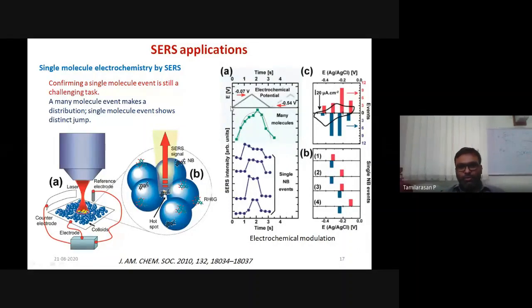It's just a cyclic voltammogram. When they scan it, they got a CV of something like this. Okay, this is for the bulk. For the bulk, what you are seeing is two different peaks here. Both are very broad peaks, and each has its own broadness and its own full width half maxima. But does it mean that a molecule is gradually oxidizing and reducing? It is not. It is a cumulative ensemble effect. Each molecule will have its own very sharp oxidation and reduction potential based on its environment. That they have proved with this method.